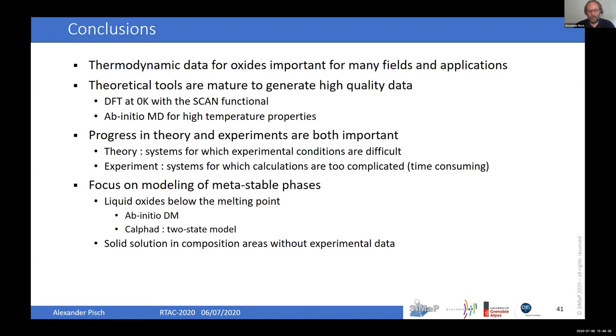But experiments are still very important, especially to check calculations and also for systems in which calculations are really too complicated. For example, in solid solutions or in compounds with partial occupancy, it's much faster to do the experiment than to do the calculations, if the sample synthesis is possible.